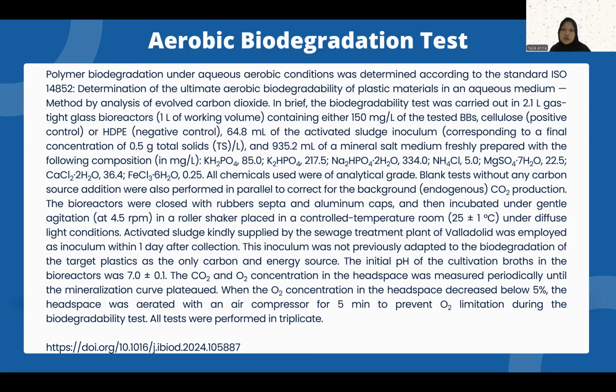The initial pH of the cultivation broth in the bioreactors was 7 plus minus 0.1. The carbon dioxide and oxygen concentrations in the headspace were measured periodically until the mineralization curve plateaued. When the oxygen concentration in the headspace decreased below 5%, the headspace was flushed with an air compressor for 5 minutes to prevent oxygen limitation during the biodegradability test. All tests were performed in triplicate.